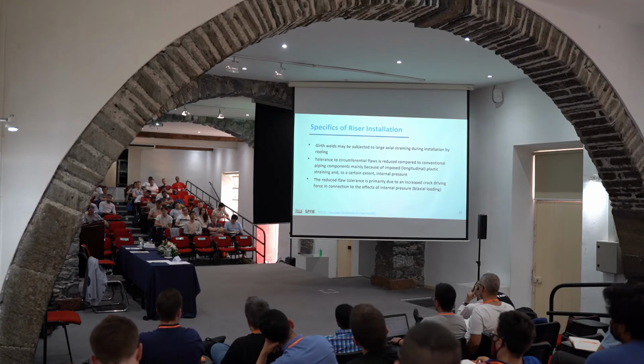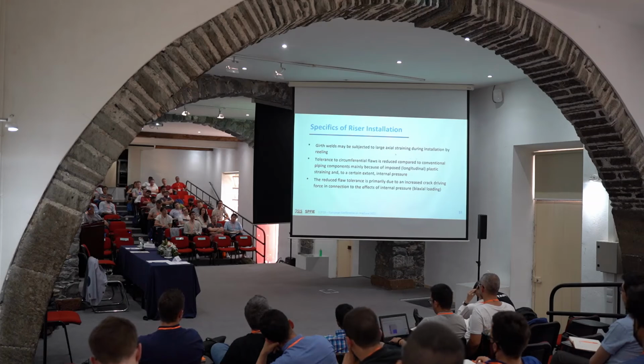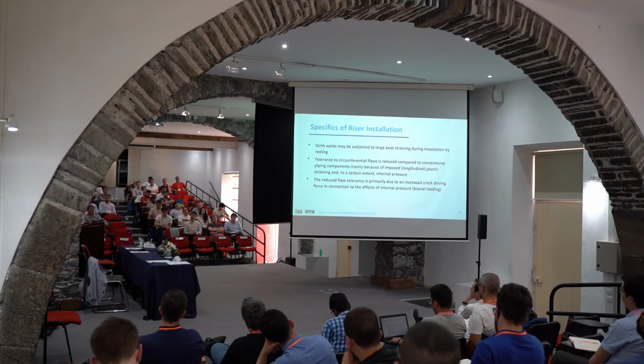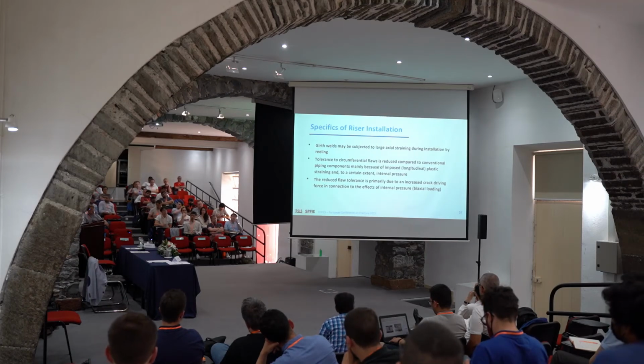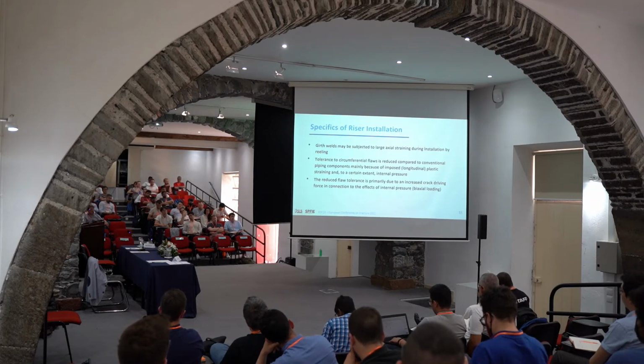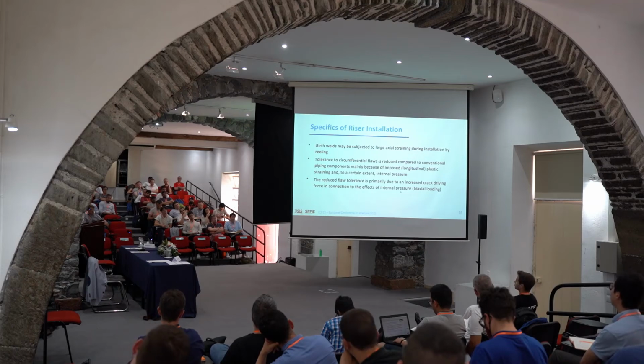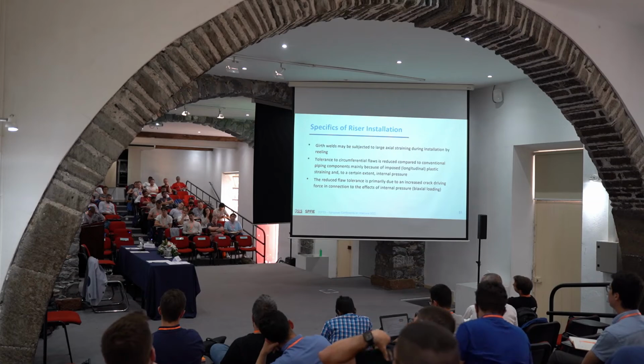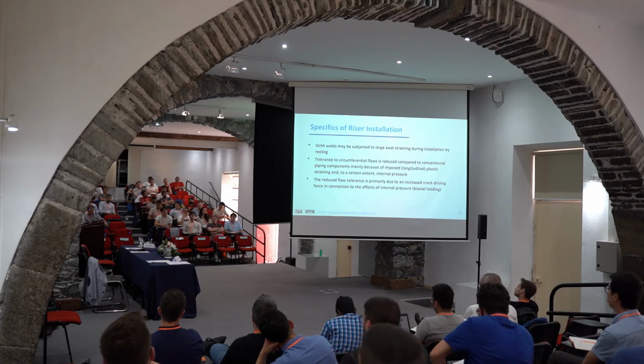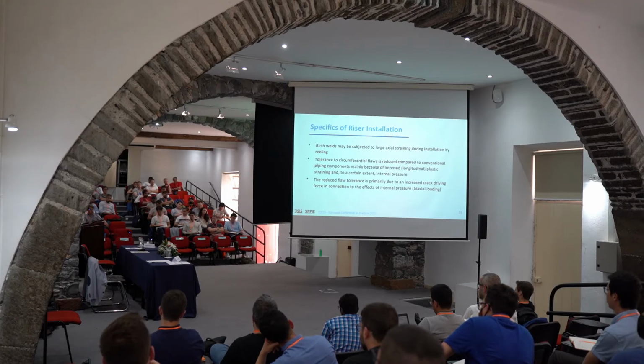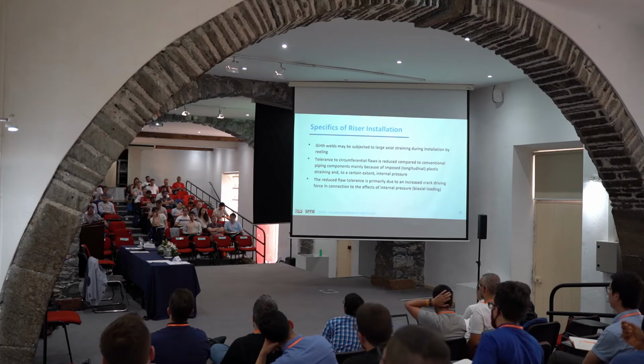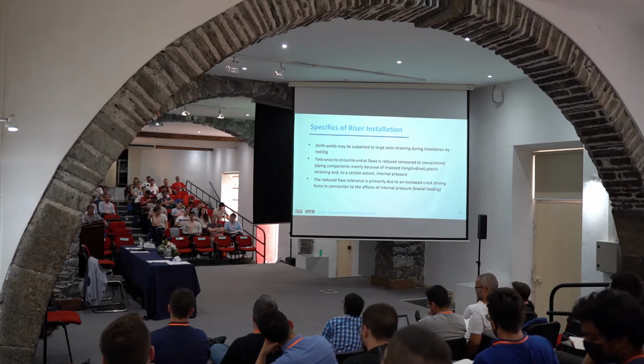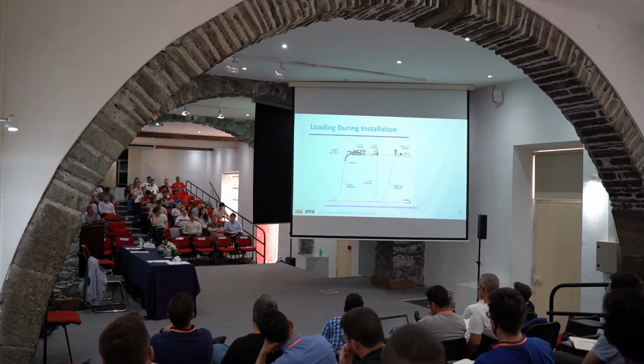I'm just going quickly on the specifics. Okay, again, girth welds are subject to large axial straining during installation, and because of this, the tolerance is reduced compared to conventional piping components. Okay, and to a certain extent, internal pressure. But this is something that I have not talked about, biaxial loading. Okay, when the pipe is operating on the seafloor, you may have bending because of the ground motion, but you have also internal pressure, because of course the pipe is operating. And we still don't know very well, till now, how to deal with the coupling of the driving force and the material toughness when you have biaxial loading. Okay? The fracture behavior is different under biaxial loading than under uniaxial loading.